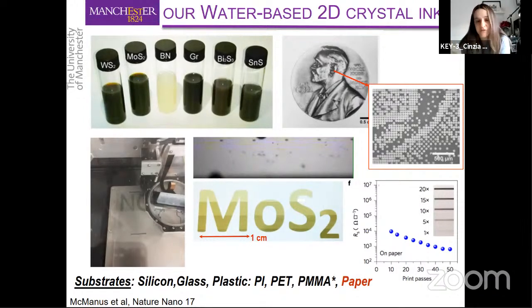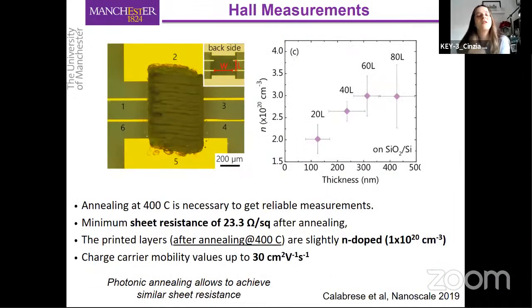So this is just the sheet resistance as it is. And of course, it's possible to decrease the sheet resistance further by performing post-processing. And this is actually what we did in a follow-up work where we wanted to perform Hall measurements on these printed graphene films.